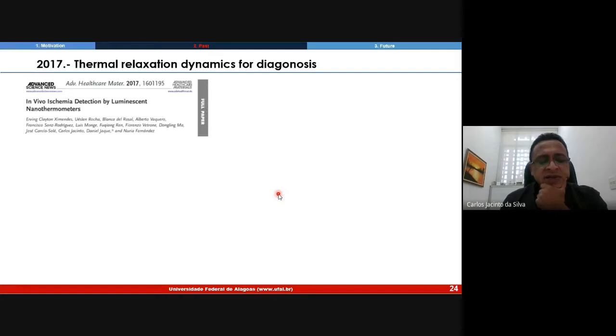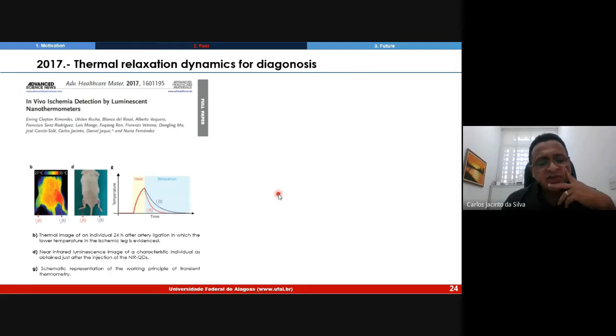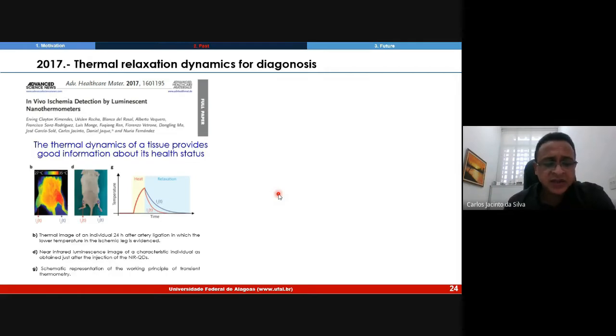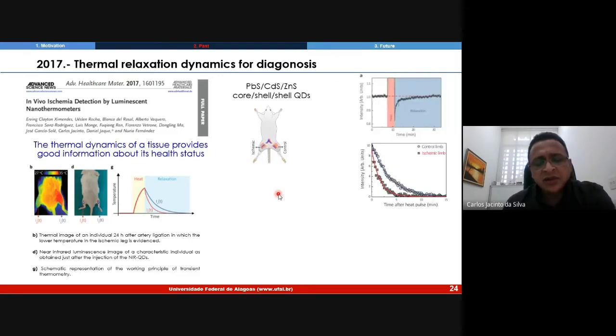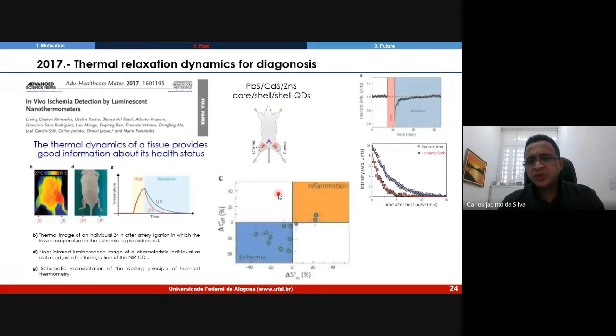We have used transient thermometry, or thermorelaxation dynamics, for diagnosis of ischemia. In fact, the thermorelaxation time provides good information about the health state of a tissue or organ. This is a simple experiment. Inoculation of the luminescent nanoparticles in the region under investigation, and using another excitation light to induce local heat, and the same or another light to pump the luminescent nanoparticles, and so detect the luminescence as a function of the tissue temperature. Okay? And they obtain the relaxation because the heat pump is turned off. In the end, the thermorelaxation time is obtained and compared in the control limb and the ischemic limb, and the final result is this one.